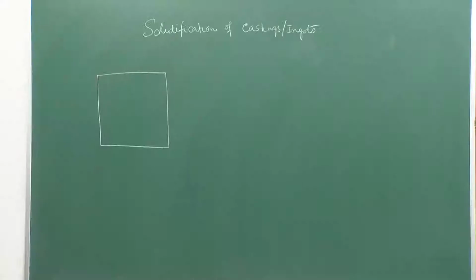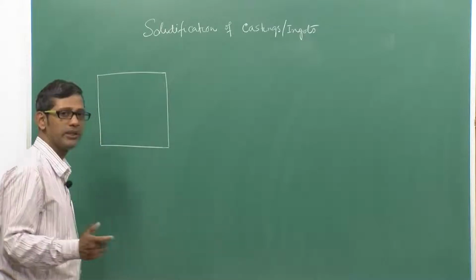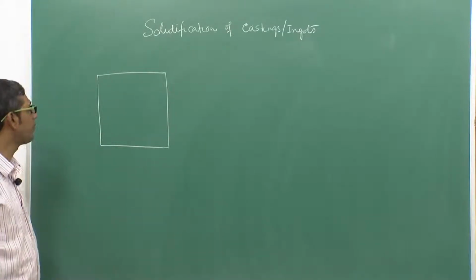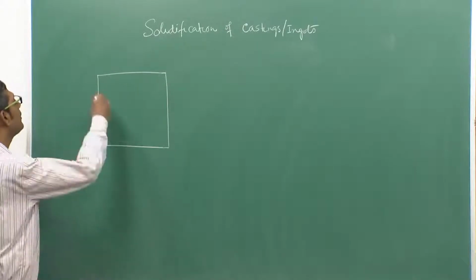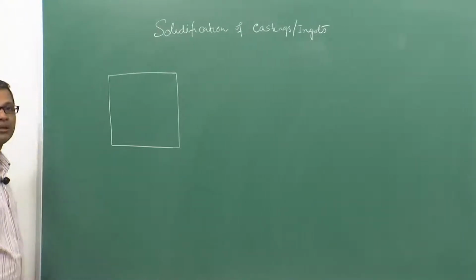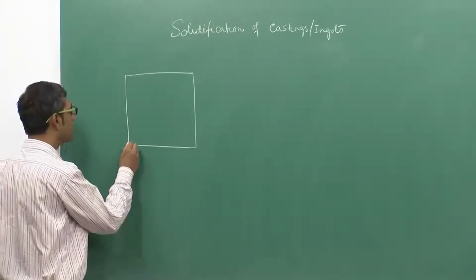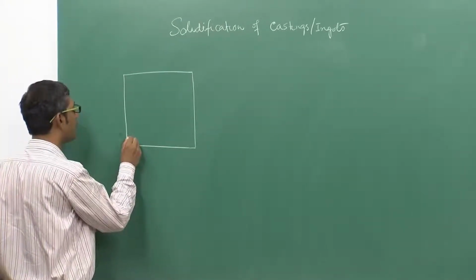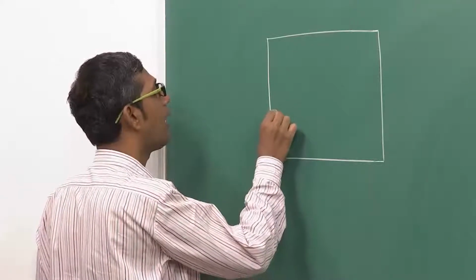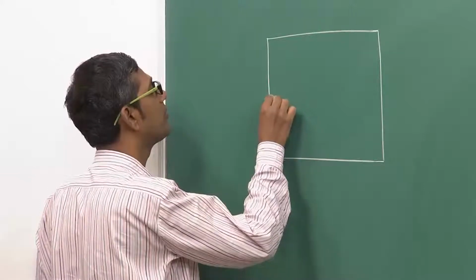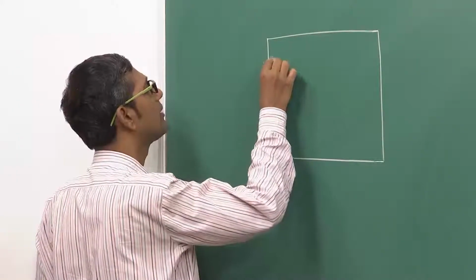So, if I pour a liquid into a big mold, it may be a metallic mold or a ceramic mold like a sand mold, what will happen? Immediately the liquid will come in contact with the mold wall and it starts solidifying. There will be very small crystals which will form. As you understand, at the boundary or the walls there is no dearth of heterogeneous nucleation sites; a large number of heterogeneous nucleation sites are available.